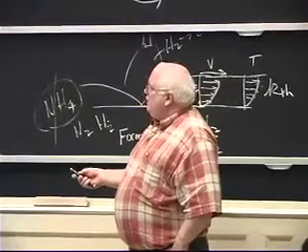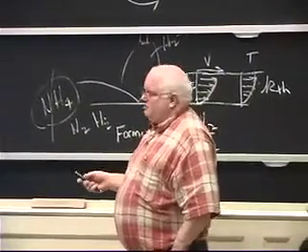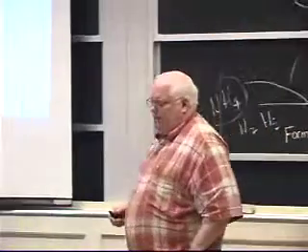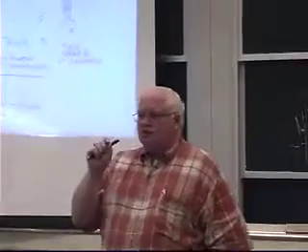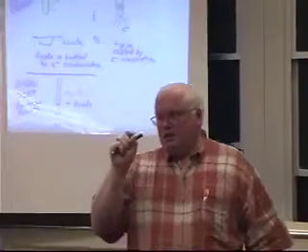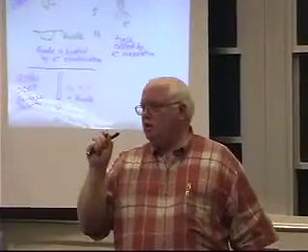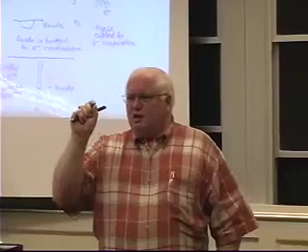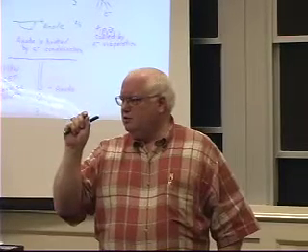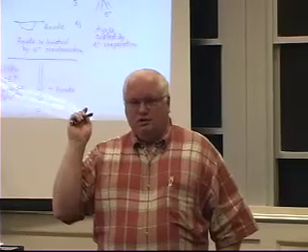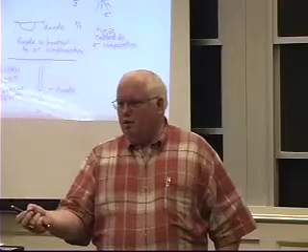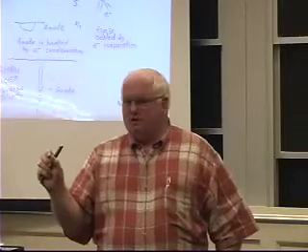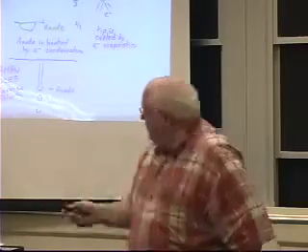So the tip is cooled by evaporation, and I remember Professor Savage telling me, he's passed away years ago now, that all of a sudden he understood why when you look at x-rays of gas tungsten arc welding, for example, a lot of times on aluminum, you would see not little circular tungsten inclusions from the tip melting and creating a ball, but little rectangles of tungsten. It was because the tungsten electrode actually melts off if you get it too hot, put too much current through it.